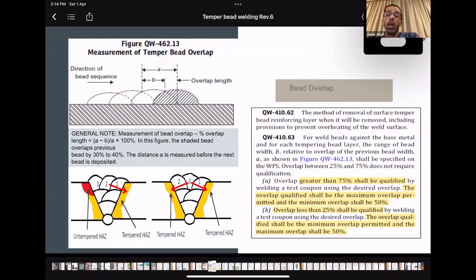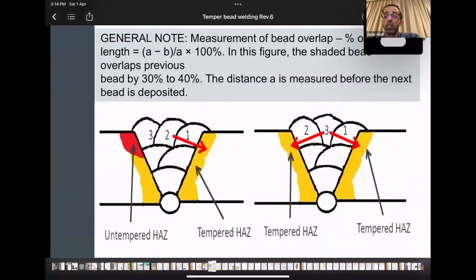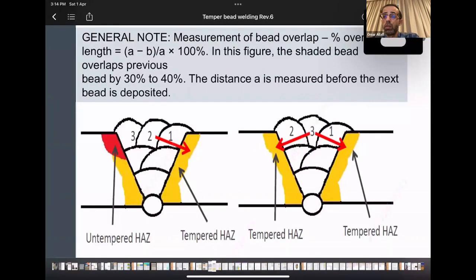So as we can see here in this figure, the overlap is between 25 and 75. Any overlap between 25 and 75 is acceptable and requires no qualification. But when it is done improperly, like the figure on the left side, the red zone is untempered zone.